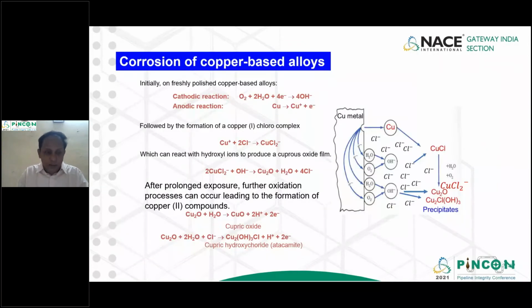Before I go and talk about the basics of the erosion-corrosion mechanism, I will just talk about the basics of a copper metal when you immerse it in a chloride environment. If you take a piece of copper and immerse it in a chloride environment, the major cathodic reaction is oxygen reduction. So oxygen reduction happens and you go to OH minus, which involves a 4 electron process. With the further complexation of chloride with copper, you get a copper chloro complex, and that copper chloro complex can form cuprous oxide.